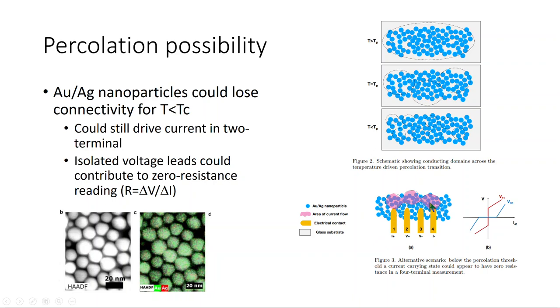So you could imagine having, let's say, three of these non-percolating areas, with tunneling between the necks that separate them. But if the voltage leads were not connected to the current path, then they would basically float to whatever value, or these two might even be connected to each other, but not to the current leads, and you would measure zero voltage. So the way that these four terminal measurements work is you measure the current that is flowing through the device, that's delta I, and then you measure the voltage that goes across the separate leads, and you want to do that because you don't want to have a contact resistance. So this is a very standard technique, but it's really important that the leads themselves be electrically connected to the sample in order to really be measuring the resistance.